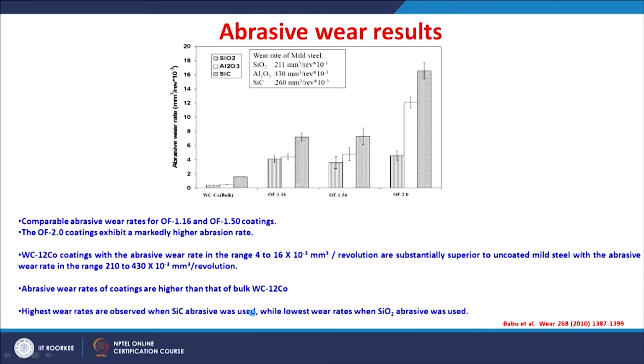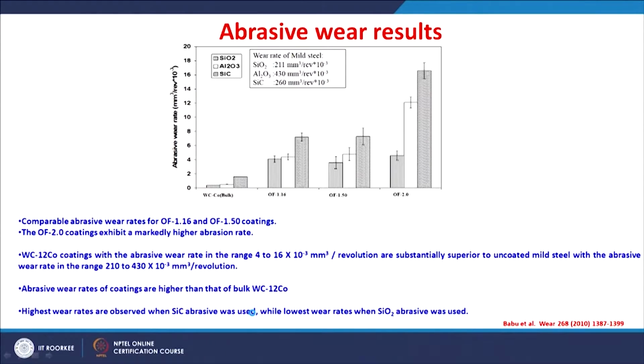The abrasive wear test was done using a dry sand abrasive wheel, and the abrasive wear rate was determined in terms of volumetric material removal per revolution. For comparison, the tungsten carbide cobalt bulk material was also studied for abrasive wear. First of all, comparable abrasion wear rates were obtained for the coatings done with oxygen to fuel ratios of 1.16 and 1.5, almost comparable for any abrasive, whereas the coating done with an oxygen to fuel ratio of 2.0 exhibited a remarkably higher wear rate.